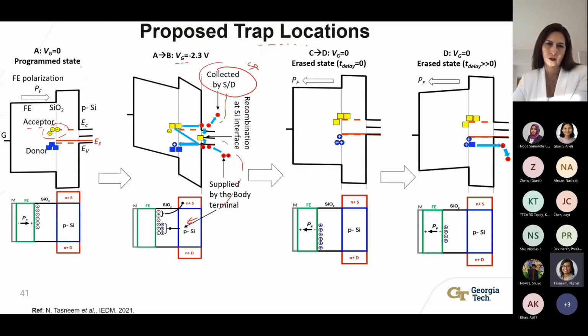And this is what we end up measuring in the split pulse technique. Now, once the erase is completely done, we now have trap states in the donor level, which are filled. Now, if we wait long enough, which means if the read after write delay is long enough, then this trapped hole starts getting emitted, allowing us to read a larger memory window.